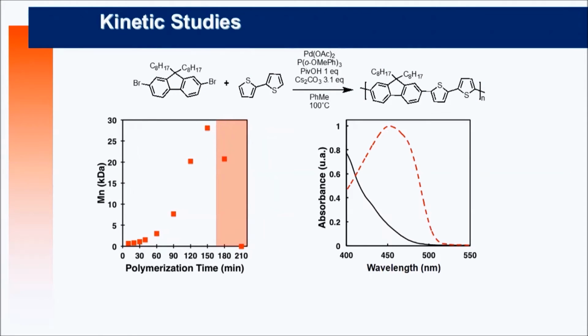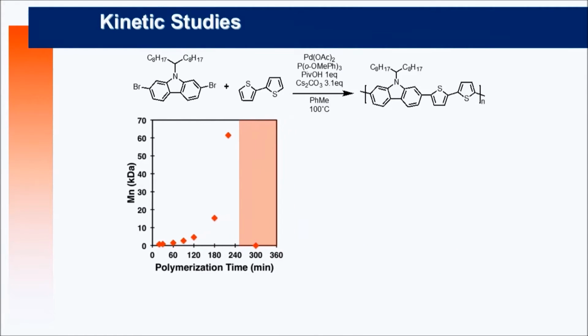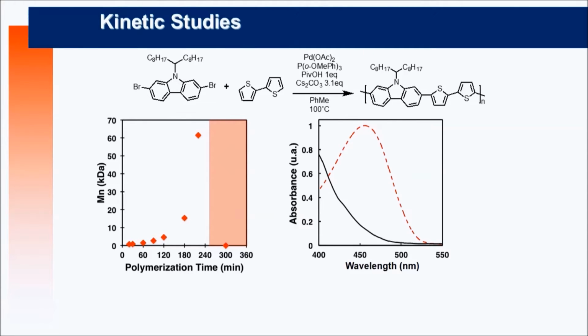I said, yeah, perhaps you have been lucky. Try another set of monomers. Oh yeah, we also followed the UV-visible. So look, at the beginning, low molecular weight as a function of time. And finally, in red, you have the typical Suzuki polymerized materials and a comparable UV-visible absorption spectrum from this direct arylation. So you try with carbazole bithiophene, same thing. Step growth polymerization. If you proceed for too long a period of time, it becomes totally insoluble. But you can stop here with a yield of 85, 90%, a molecular weight around 55.